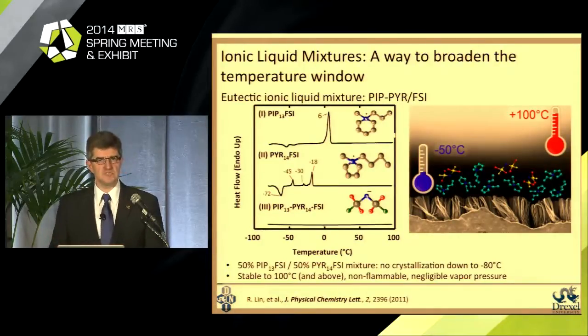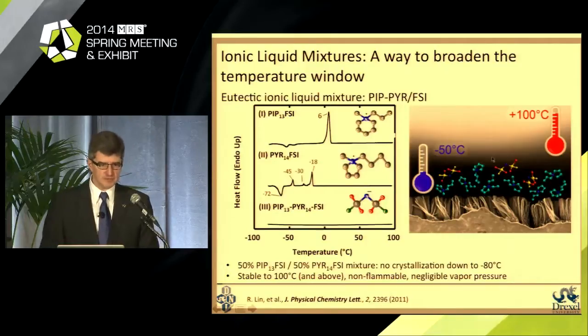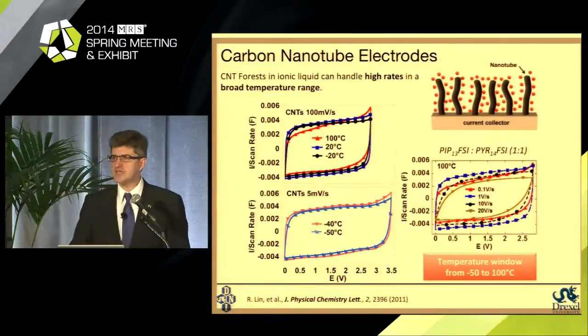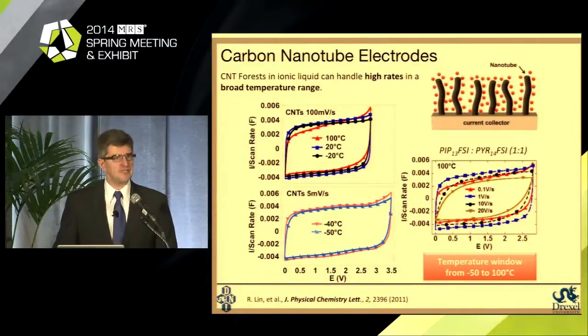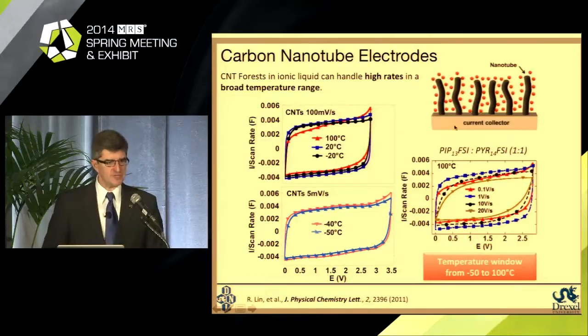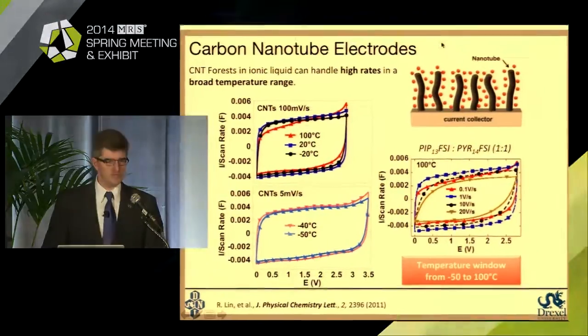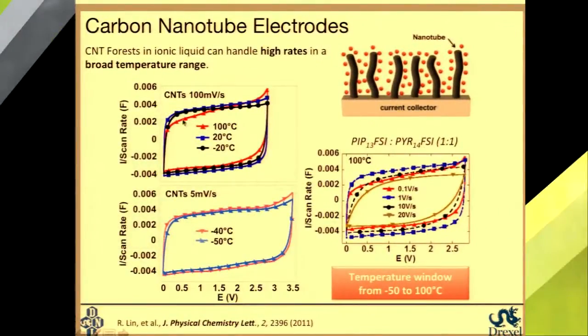What our thinking was that if we don't have pores in which ions need to diffuse, if we just have adsorption of ions on the surface, we should be able to expand the temperature range. And we tested this hypothesis using carbon nanotube electrodes. What you see happens, we can charge a supercapacitor which is made of an aluminum foil with grown carbon nanotube at 100 degrees C and actually do it at extremely high rate, going up to 20 volts per second, which is really unbelievable for ionic liquid electrolyte.